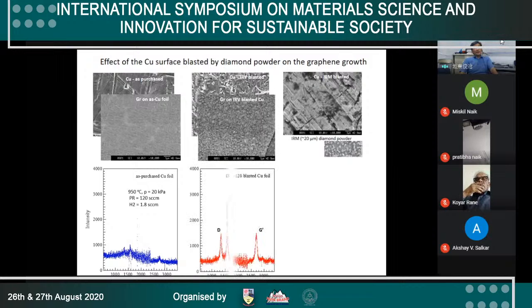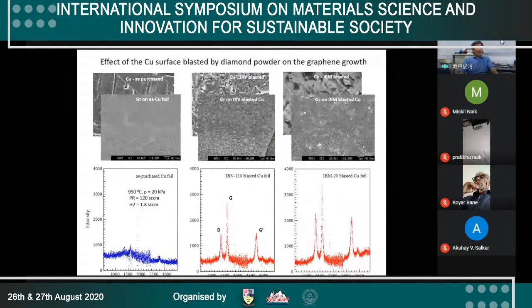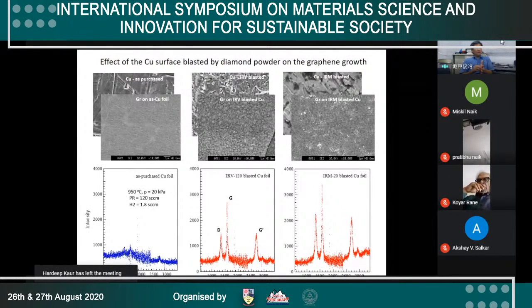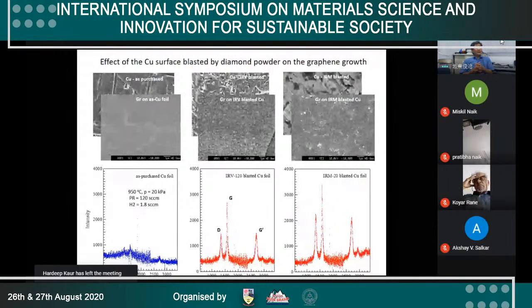The rough surface changes to a slightly flat surface. This is the Raman, and there is a strong Raman signal, and also the final one. So when we make a rough surface, we can get graphene, and the reproducibility becomes high.